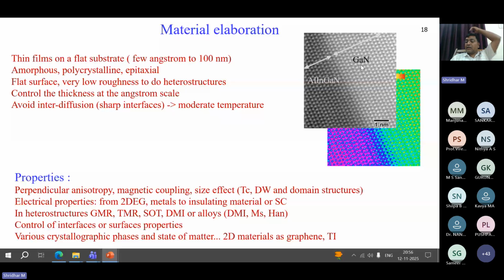Here is gallium nitride. Again, it is a known semiconductor, gallium nitride, and aluminum indium gallium nitride. Here also you can see the width of this black line is somewhere around 1 nanometer, and you can clearly see gallium nitride atoms here. Okay, gallium nitride. This is the SAED pattern, the SAED image of this TEM. Okay. So it is very difficult to create the periodic arrangement, to prepare the periodically arranged atoms.